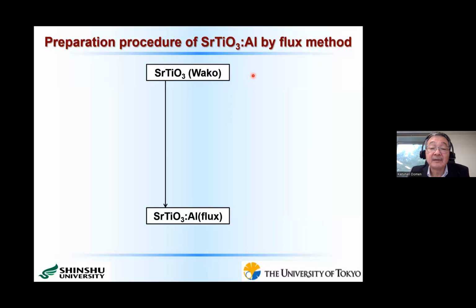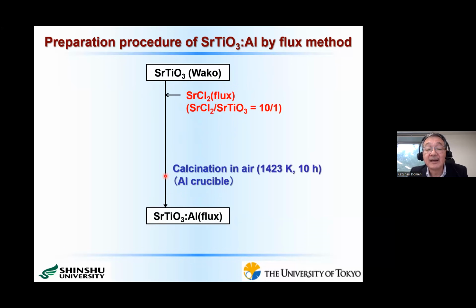Here I show the preparation procedure of our materials. At first, we purchase stoichiometric strontium titanate and then add a large amount of strontium chloride as a flux. Then we mix these two materials in an aluminum crucible, then calcine in air at 1423 Kelvin for 10 hours. By this method, at first we didn't realize, but some amount of aluminum in this aluminum crucible is dissolved into strontium titanate. So we call this material aluminum doped strontium titanate prepared by flux method.